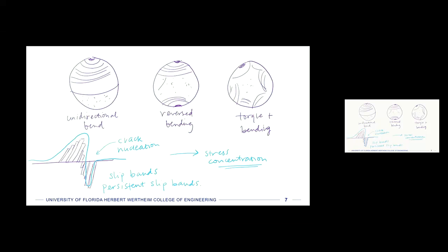So it's not like there's grain refinement and there's different tiny grains, right? If there's a lot of small grains in a ductile metal, then that serves a toughening effect. But these are defects that actually are not like at a grain boundary that has these toughening effects. They're actually on the slip planes that are more likely to maybe slip again. And these cracks can even go through different metallic grains if the slip planes are organized in such a way that they're likely to do that.